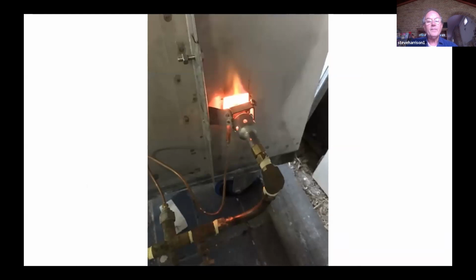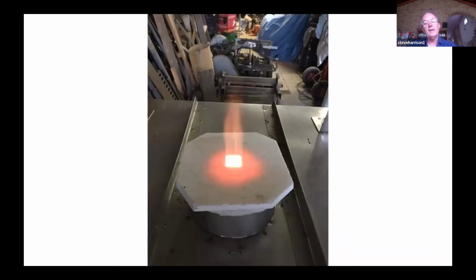And the last one is a picture of the flue here. So I put a little sheet of fibre over the top of the chimney, and you can see the flame coming out there. So you can damper it back by putting a little tile over that and cutting it back more. I did various experiments with using slightly higher and lower pressures, and I found around about 5 kPa pressure